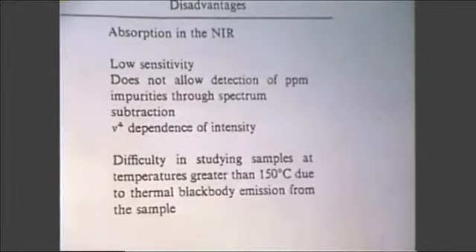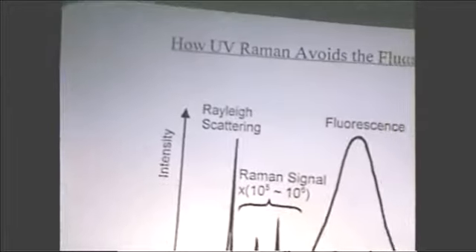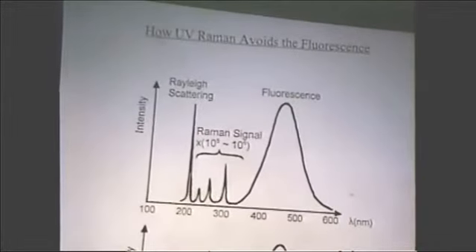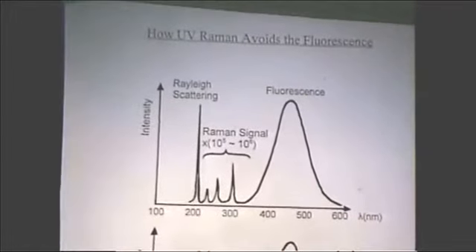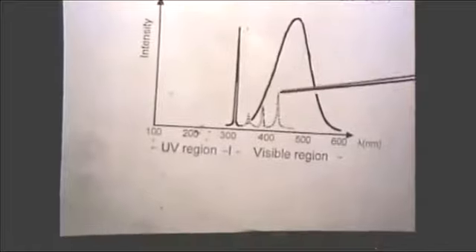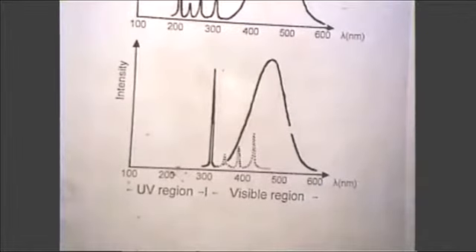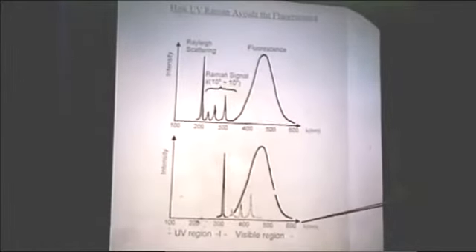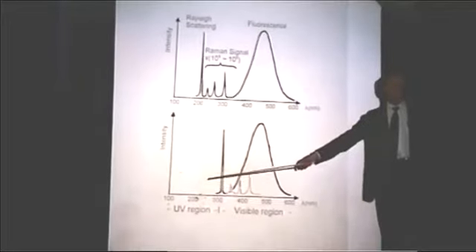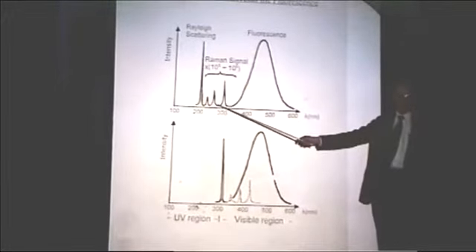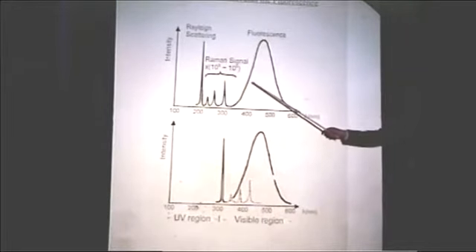Okay. Now, about 10 years ago, a fellow by the name of Sandy Asher at the University of Pittsburgh got another idea. His idea for avoiding the fluorescence is shown schematically in this diagram. In the normal case, one excites Raman scattering with respect to the fluorescence that a sample has produced in such a fashion that the Raman peaks are buried by the fluorescence. And in the near IR experiment, the excitation takes place over here, where we're avoiding the fluorescence. Well, Asher's idea was, let's go over on this side of the fluorescence, and let's excite the Raman scattering at such a short wavelength that all the Raman peaks will appear before the fluorescence starts.